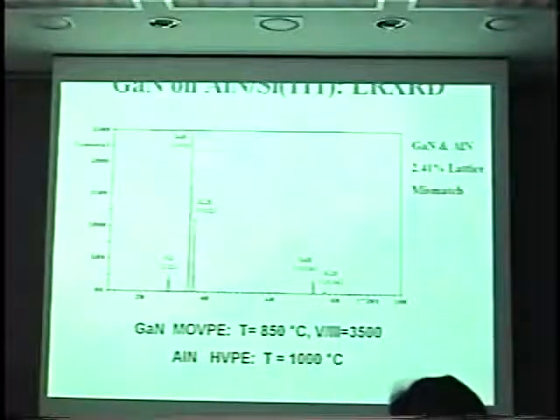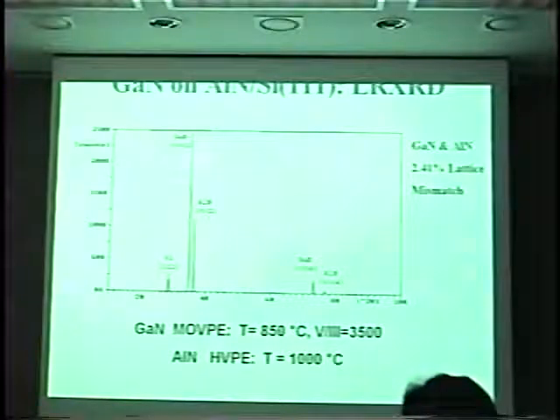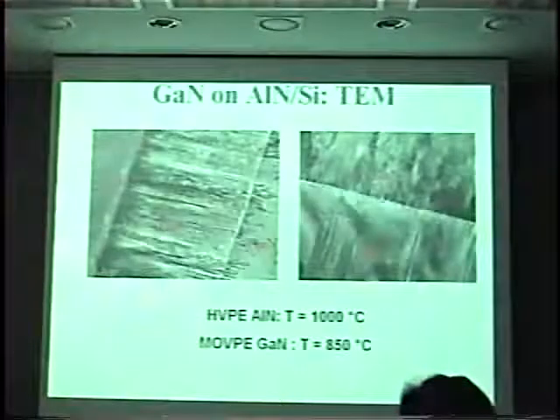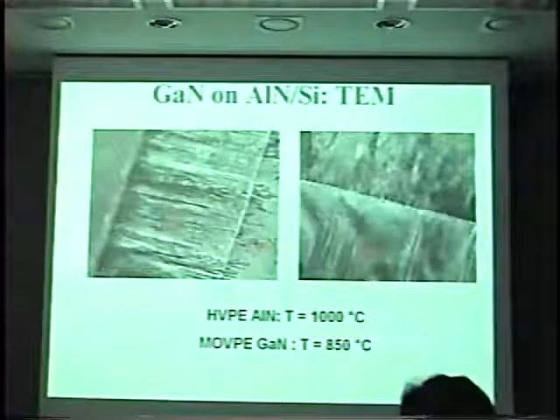So we took some aluminum nitride and grew it on silicon by hydride VPE, using the chloride of aluminum as well as ammonia at 1,000 degrees C. And we came back and grew in our traditional commercial MOCVD system at our typical growth conditions. And you can see indeed we get single phase, single crystalline gallium nitride. If we look at the quality of the gallium nitride, it is relatively high. In fact, it's the best gallium nitride we've grown yet on silicon.